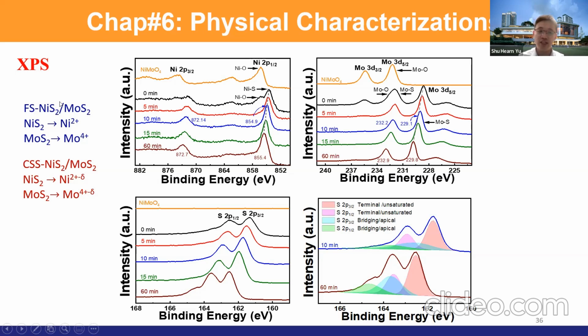Then by controlling the temperature and the time, you can control the species of these active sites. So if you can find out which active site is more active, then you try to increase the number of active sites by controlling the time of sulfurization. So this is something missing. This is a missing piece in the full sulfurization that people are not aware of. This transient state can really bring some interesting phenomena.